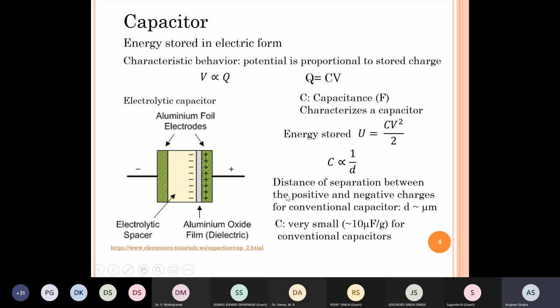And when this kind of an arrangement is made, then the distance of separation cannot be reduced beyond about a micrometer length. If one tries to make a device where the length is made into nanometers or a fraction of a micrometer, then usually because of the roughness of the surface and manufacturing defects, some kind of short circuiting takes place, and that's a very dangerous situation in a capacitor because they can supply energy very fast. So usually it will lead to some kind of bursting, and therefore these devices, conventional capacitors, are limited with d in the range of 1 micron to 10 microns.